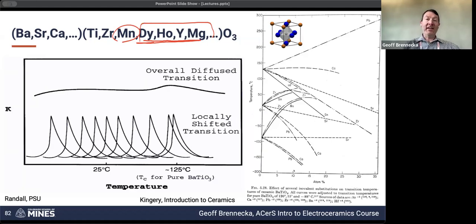On the lanthanum side of the lanthanide series, those species are large enough that they can actually substitute on the A site of barium titanate. At the smaller end, ytterbium and lutetium and the smaller lanthanides much prefer to go on the B site because they're small enough, they fit better there. So you can either have a 3+ on a 2+ site, which is a donor dopant up here, or you can have a 3+ on a 4+ site, which is an acceptor dopant down here.